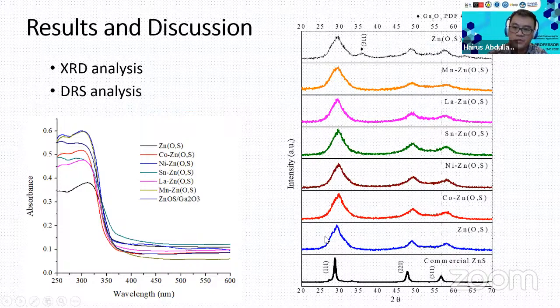Then I will show you a very brief characterization of this ZnOS-based material. As we add different kinds of metal, we see that the optical absorption also improves, right? In the area of 250 to 350, the light absorption is increased. If we look at the XRD patterns, all of them show the same phase, only one phase. Compared with the commercial ZnS, we have three main peaks, and all three main peaks shift to the right-hand side, indicating that the lattice parameter becomes smaller because oxygen is incorporated into the lattice, right? Except the top one. The top one indicates we have a composite material, ZnOS, with gallium oxide, because we find a peak corresponding to gallium oxide.